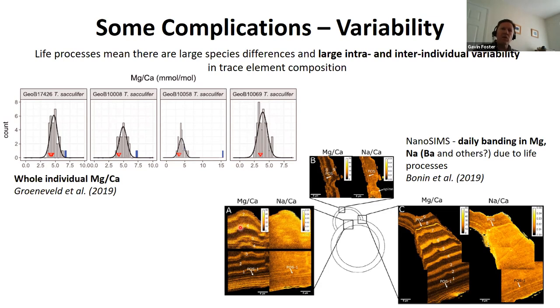That's about 10 times higher magnesium content than the low parts. But you can also see this banding in other elements like sodium. We're not really sure what causes it, but we think it's daily. It is probably related to how the organism is living its life, how it's making its shell, and how it's using magnesium to control that process.